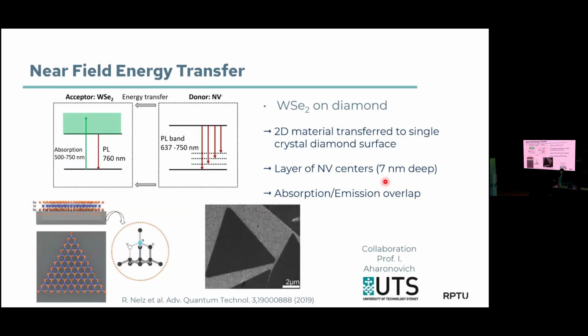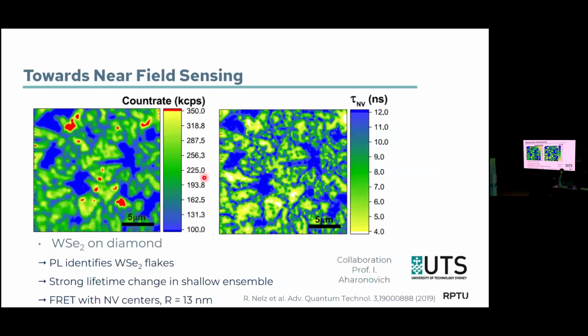And again, the NV centers are about 7 nanometers deep, and we have this overlap of the bands you need to see a thread. Now we were interested if we can really see FRET, because except for our quick and dirty experiment with the graphene, no one had seen this before, that NV centers in the single crystal are showing FRET. And then we had our flakes here. You can see this triangular shape, roughly, of these flakes. A lot of them lose this triangular shape when they're being transferred to the diamond. Not such a smooth technique, let's say it like this.